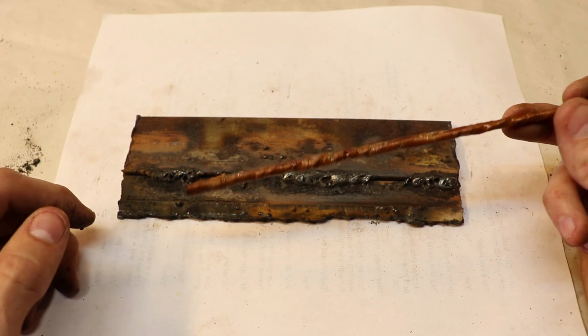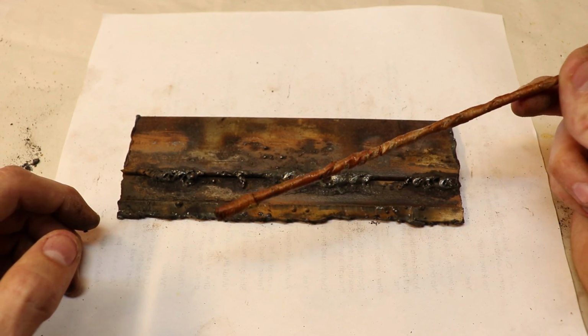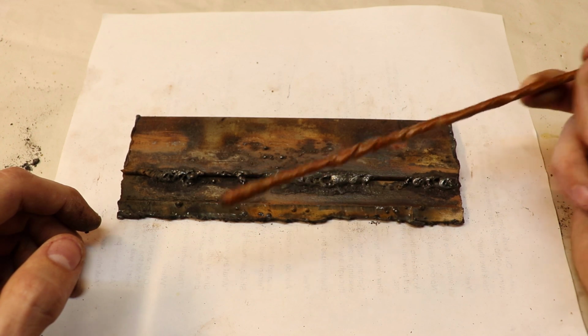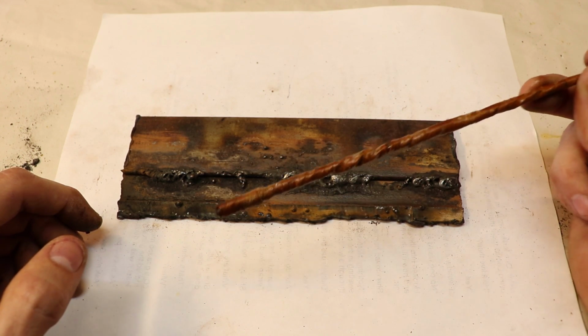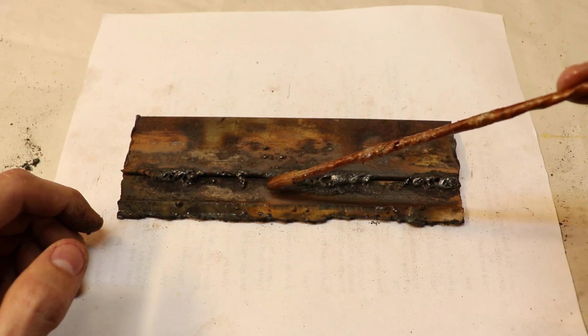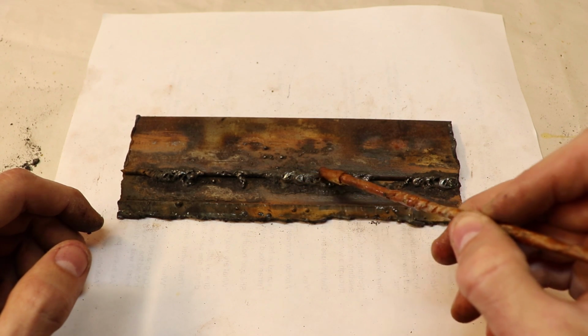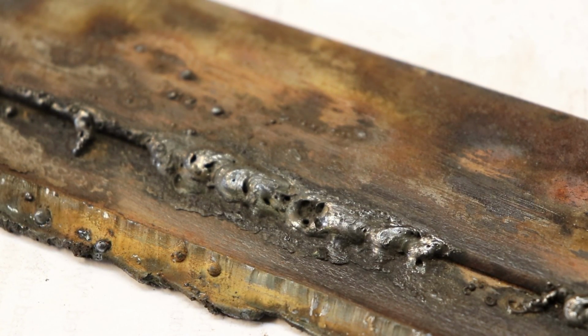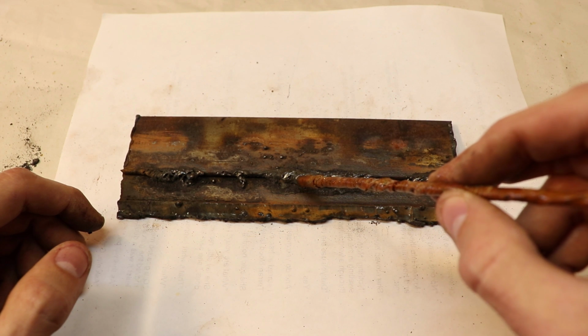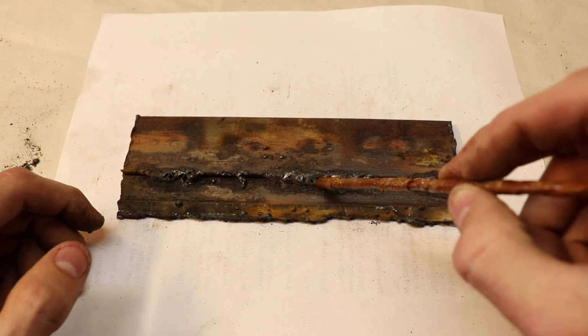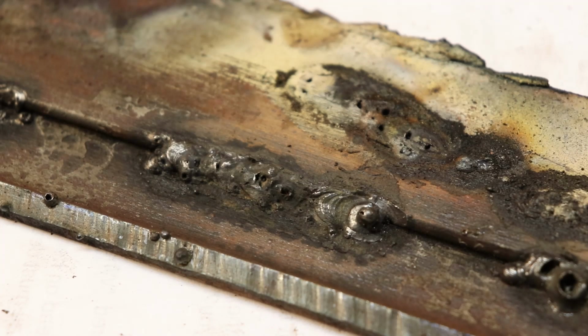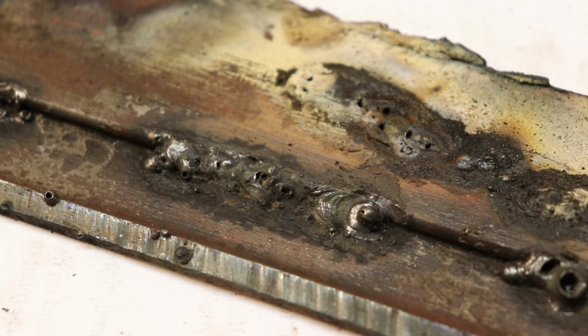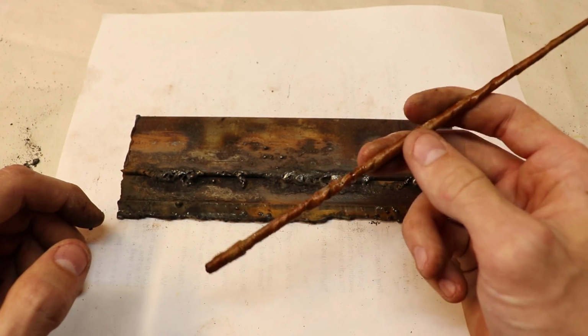I did notice with these rods it was much harder to start with them, but once you did start a weld with them, then I found that the arc itself was stable enough to continue welding. Now, when I welded with these rods, I found that doing a circle motion was just not possible. It was difficult to do that motion, so what I did with these rods when I welded, I actually just went very slow and steady and straight, and I made sure to keep an even distance, a uniform distance above the joint, and just try to fill in the joint with the coat hanger wire. That seemed to work the best with these rods.